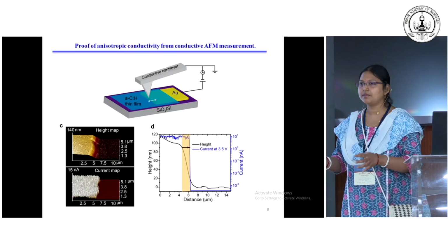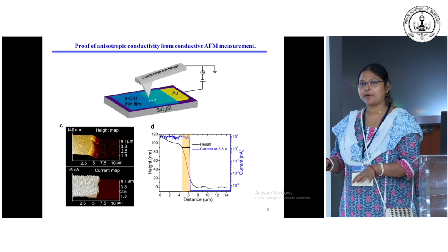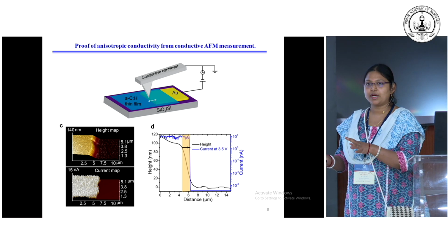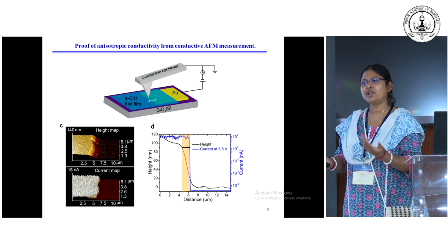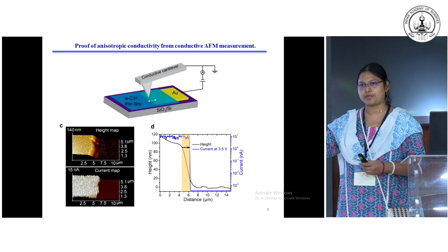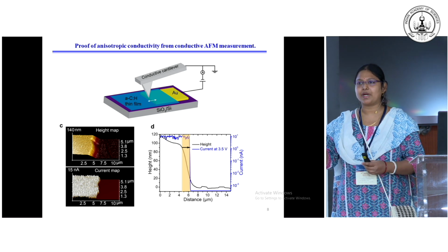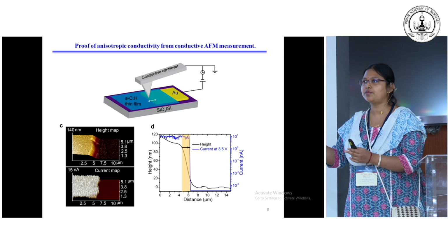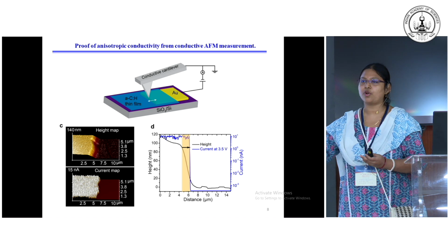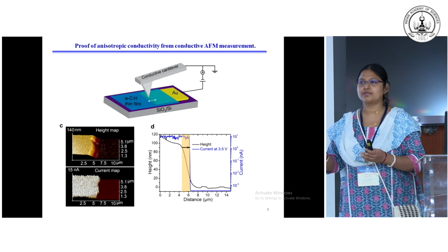But you control the time of the microwave radiation, or it must have required some amount of calibration. Yes, and we also did it in a microwave reactor to know the exact parameters. There we have seen that we need 200 watt of microwave power. In a household oven we can control the power, not very precisely, but even so we found that from 200 watt it starts carbonization. Below that it will not form, so prolonged time may be required. So it is very easy, sir.